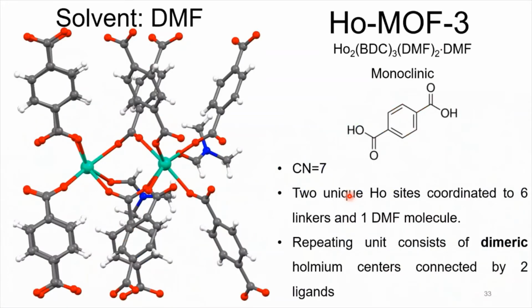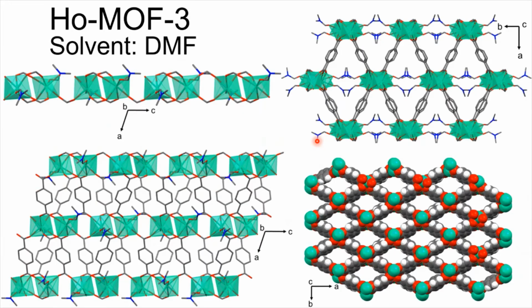Now, what if we get rid of water? We change the coordination number again. So we have 8, 9, and now 7. Now we only see the DMF coordinated to the centers. But then again, the repeating unit is dimeric. We have 2 Holmium sites. And very similar to the previous ones, but now here you can actually start seeing those diamond-shaped pores once we remove the DMF from those centers.